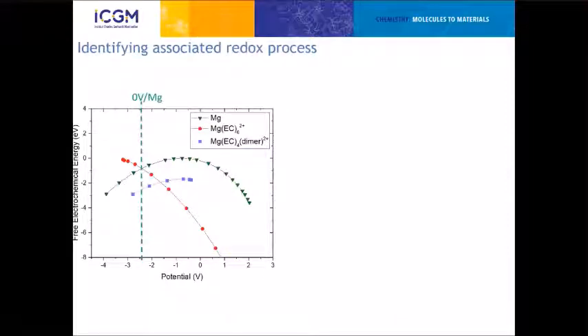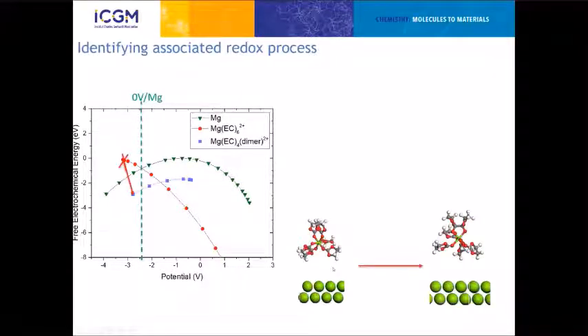Now, we really wanted to identify the associated process, this time not associated with the reduction of the magnesium, but with the reduction of the solvent molecule that is coordinated to the magnesium atom. In this case, we start with the molecule in ethylene carbonate, and we find a specific free energy for the new dimer. Then we try to find the behavior of this dimer under this type of oxidation. Around 0 volts, we get simply the reaction going back to the initial state. So we have some kind of reversibility between two coordinated ethylene carbonates and some kind of dimer.